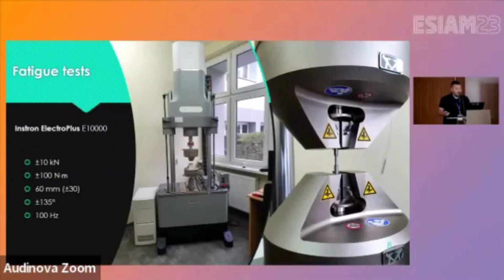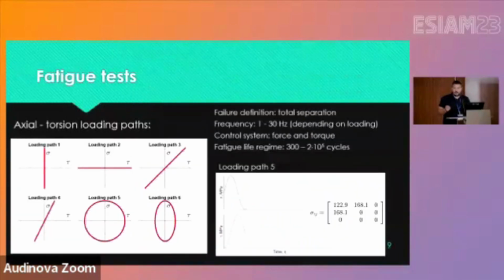So we used this fatigue test machine from Instron. It's an electrical machine, 10 kilonewtons in tension and 100 newton-meters of torque. For some of them, we used a bigger load cell of this machine, 10 times bigger, for the very low fatigue life and higher stresses, because this wasn't enough. And we used 6 loading paths for the fatigue test. The first one is just tension-compression, the second one only torsion, then in-phase combinations of tension and torsion, plus out-of-phase combinations. The tests were roughly between 300 and up to 200,000 cycles of fatigue life, so low cycle fatigue.